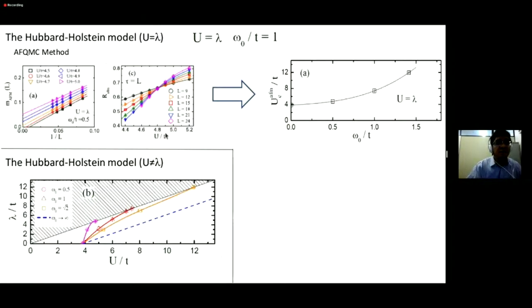So the same thing we saw when we analyzed the transition to the antiferromagnetic side. For instance, going to the opposite side, in which U, the electron-electron interaction, is larger than the electron-phonon one, we saw that the critical lines for antiferromagnetism change. So here, it changes very drastically if you change the phonon frequencies.